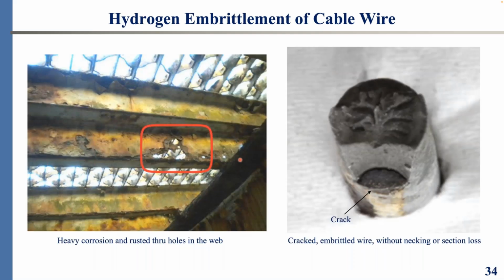So what is the difference between when we say corrosion fatigue, stress corrosion cracking, and corrosion, visual corrosion? Well, stress corrosion cracking, corrosion fatigue, those are fracture mechanics terminology. They have scientific meaning. They have the crack growth, the fatigue that happens to the wire under the effect of environmental degradation, the degradation process that releases the atomic hydrogen that comes into the crack tip and the crack mouth and keeps furthering breaking the interatomic bond and furthering the crack growth and results in that embrittlement.